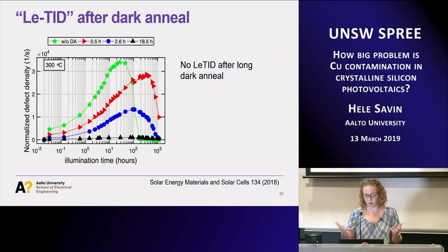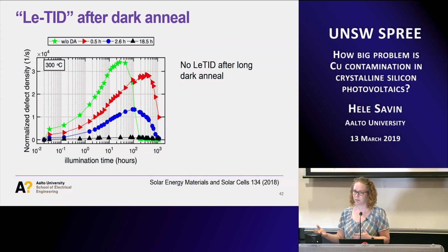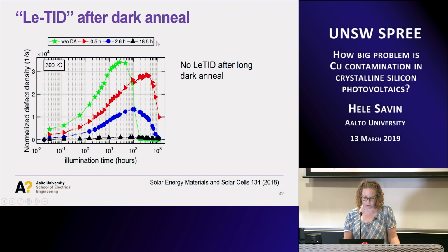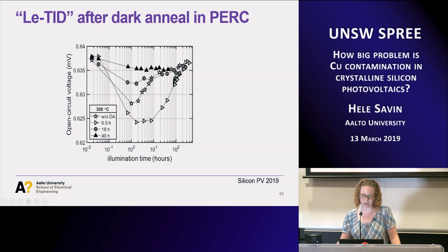So this was one thing we wanted to try now with the actual PERC cells, because the temperature 300 is not too high that it would affect the emitter or some other parameters, maybe slightly the contacts, but anyway, for the initial test, I think it's showing quite nicely that we can definitely reduce the degradation kinetics or the LeTID curves. And to be honest, these have not been intentionally copper contaminated, but I believe there is no photovoltaic wafer which doesn't have copper, if we compare to microelectronic grade silicon.